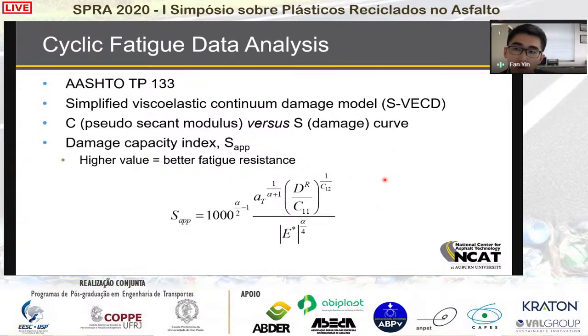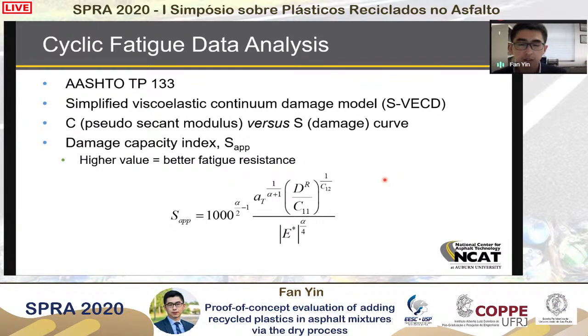And then finally, we look at the cyclic fatigue analysis. I know we are running behind, so I don't want to spend too much time talking about the theory behind this. But this is a test that uses a viscoelastic continuum damage model. And we get a C versus S curve, which gives a relationship between the pseudo stiffness versus damage. And also we can look at a cracking index parameter called Sapp. In this case, a higher number indicates better fatigue resistance.